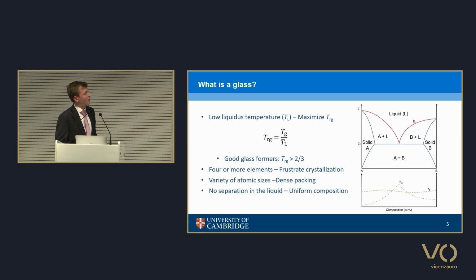So our aim from the previous slide is to push this C-curve as far to the right as possible. And we can do this by adopting several strategies in choosing our alloy. So first of all, as Ulrich was saying, we typically choose these eutectic compositions, so where the red line intersects the blue line. And that means that our liquid is as stable relative to the crystal for as long as possible. And so the temperature gap between here and where the glass transition would be is as small as possible.